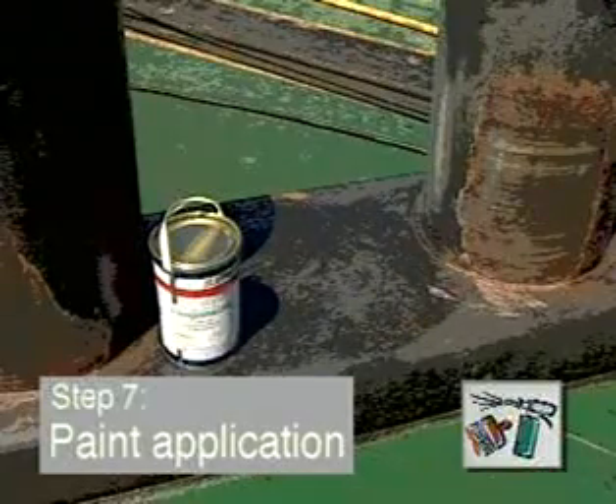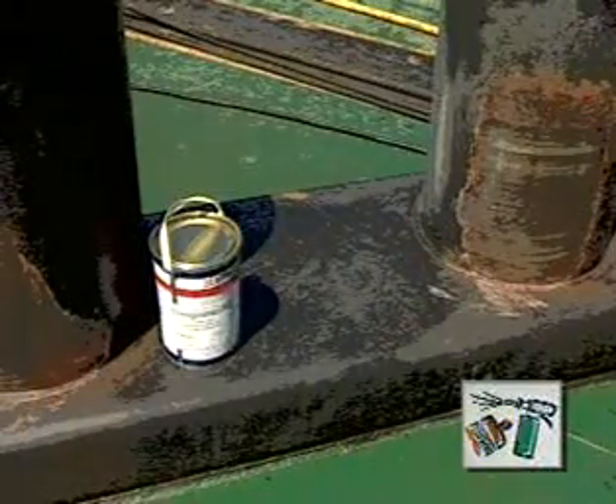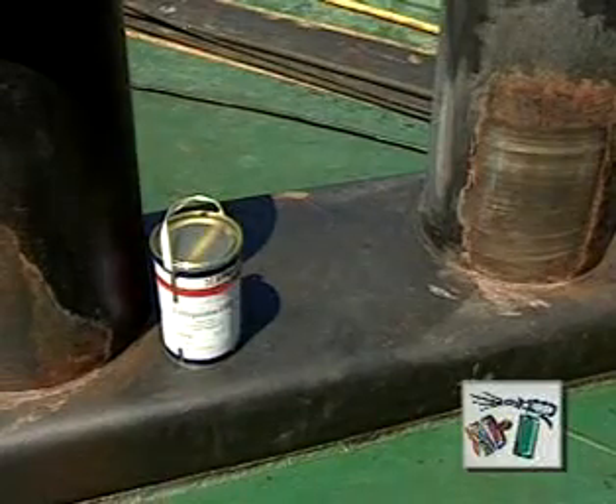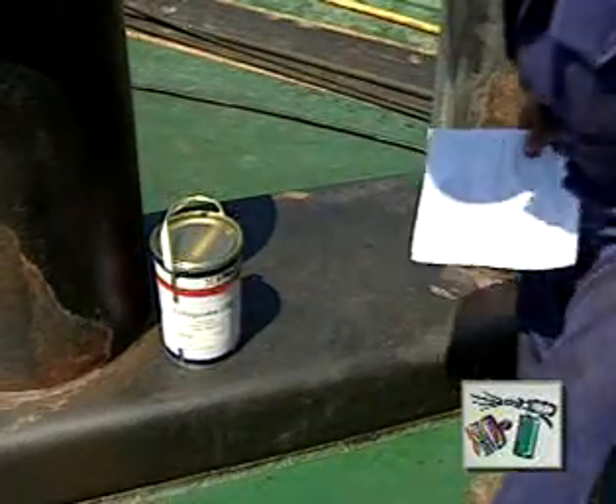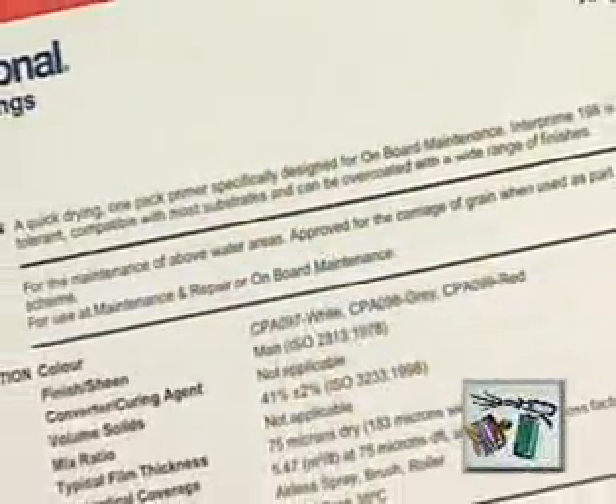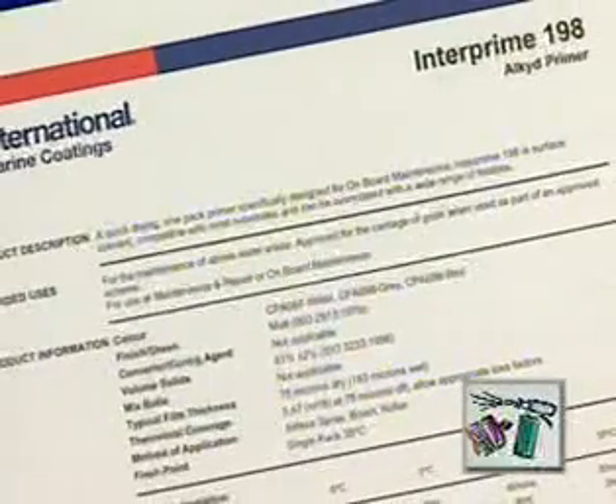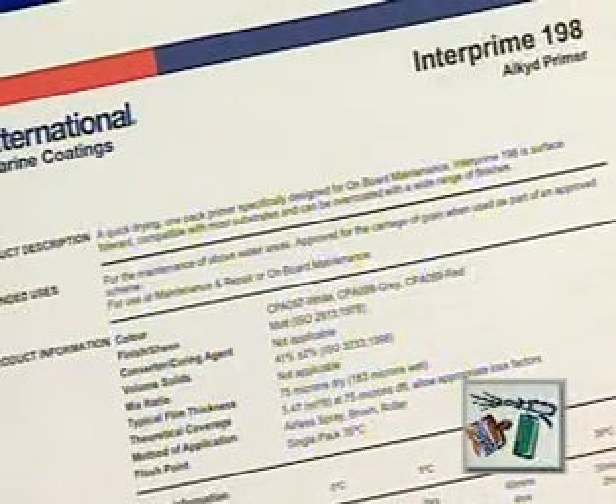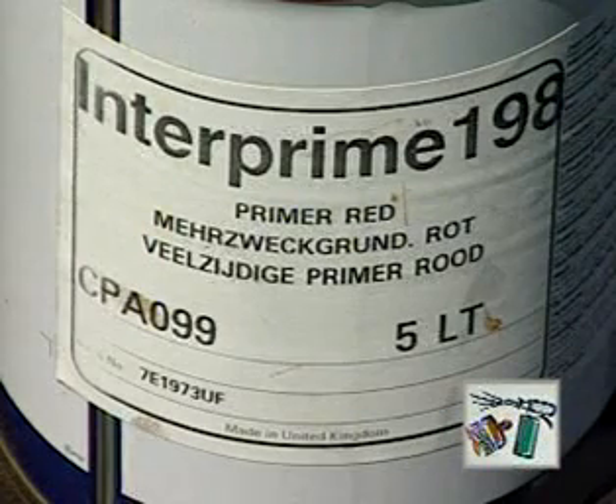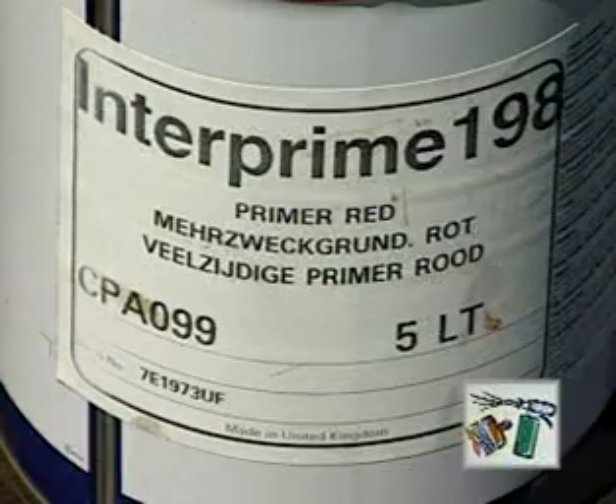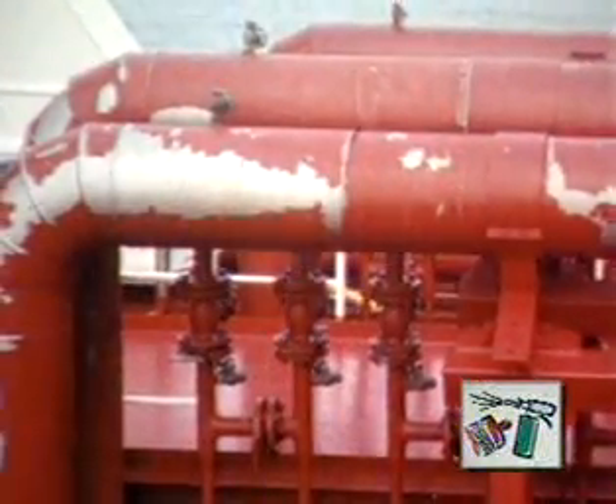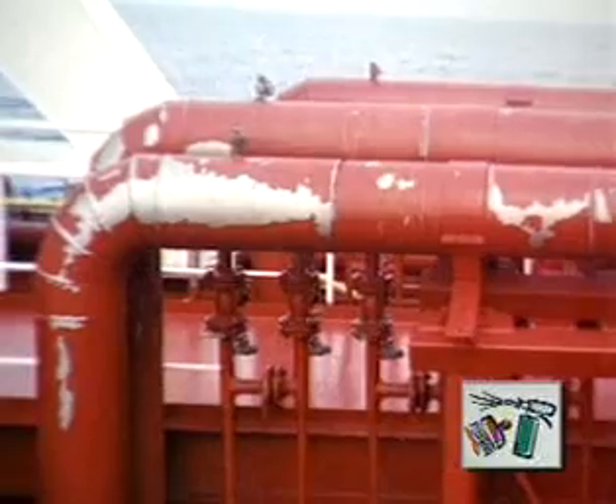Step 7. Paint application. Before you begin paint application, check again you have sufficient quantities of the correct products to complete the planned job. Carefully note which paint materials are required for the job in hand. If the incorrect paint is used, or the sequence of primer and finish are not applied in the recommended way, detachment, wrinkling, cracking, or splitting of the applied film may result, which in due course may lead to detachment, further corrosion, and more repair work.